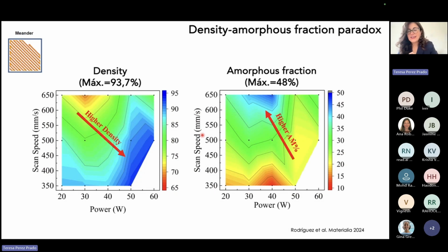And here is where I wanted to tell you some bad news, which is the following. If we take a look, we measure the amorphous fraction by calorimetry, DSC, and here you see a color map with these measurements. Now, again, what is the amorphous fraction obtained within this processability window of scan speed and laser power? And we see the maximum we achieve is 48%.